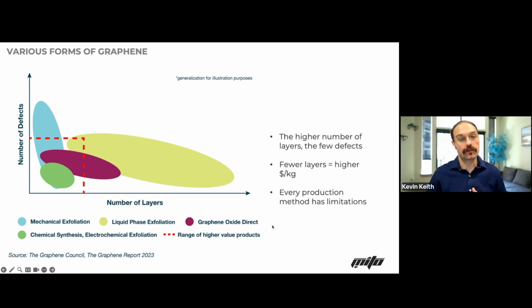So the fewer the layers, the higher the price per kilogram. So if you're looking to do a monolayer graphene to go into your fiberglass polyester system, it's not going to work just on a cost perspective. That's because usually whenever it comes to monolayer graphene, they're charging about $1,000 to $2,000 per gram. It's insanely expensive. But of course, every production method has its limitations, because if you're trying to get that monolayer graphene, you're making nowhere near as much. But if you're sending chunks of rock through a grinder, you're going to be making a lot more, albeit at a much, much lower quality. But there's a reason why some graphenes in the world are being sold for $300 a kilo type of thing.